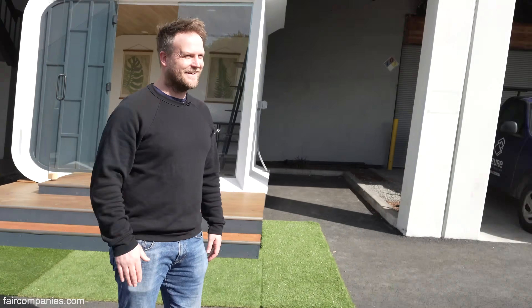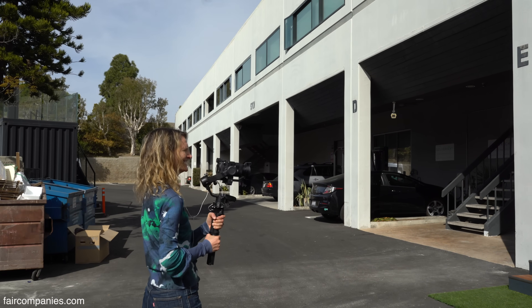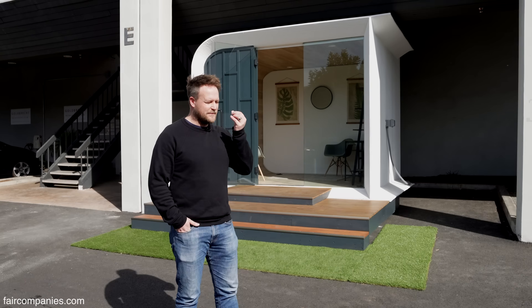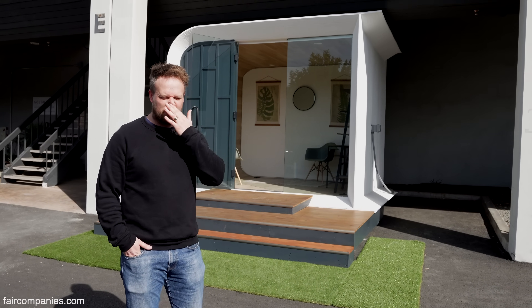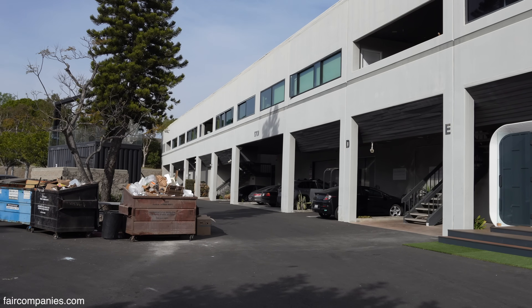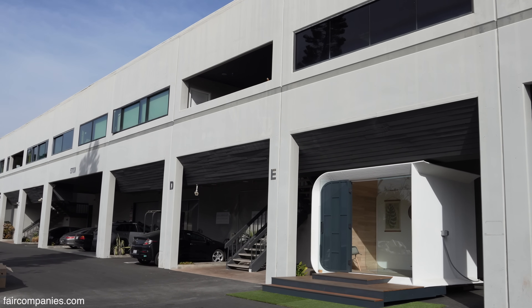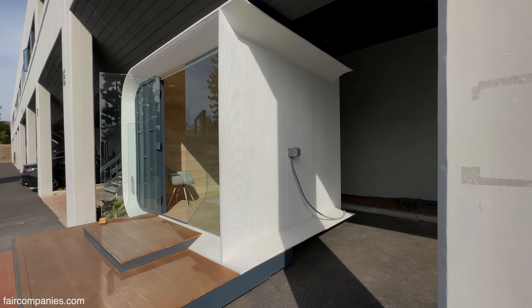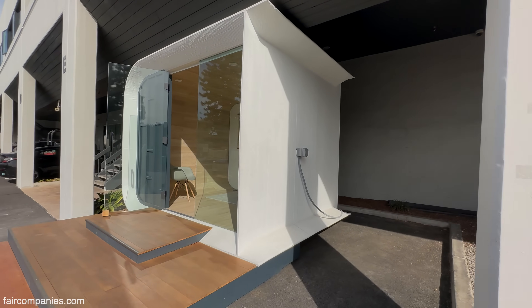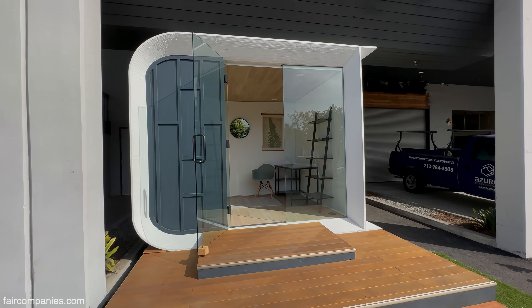This one — it's actually on the label on the bag — it explains that it's plastic from bottles and stuff. And a house. I think you may be the first house that's made from recycled plastic. The benefit of not just using recycled plastic but also 3D printing is that we have zero waste. We can regrind to a certain ratio — no more than 20% — mix that back in with our regular pellets and reuse it. So we're starting this as just a proof of concept, but it can be a solution for so many other things beyond a backyard structure.